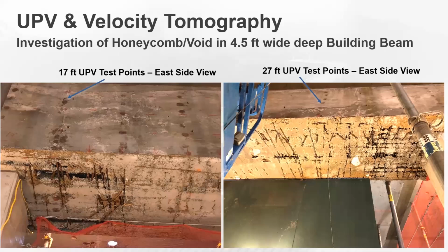So this project had to do with a large building beam, a transfer beam, where unfortunately there was a delay in the concrete placement that resulted in the concrete setting up before it could be fully vibrated. And they had to start it again. They placed it, but unfortunately they ended up with honeycomb and void in the bottoms of this 4.5 foot wide, nominally 3.5 foot tall plus the slab above it, beam on a high rise building.